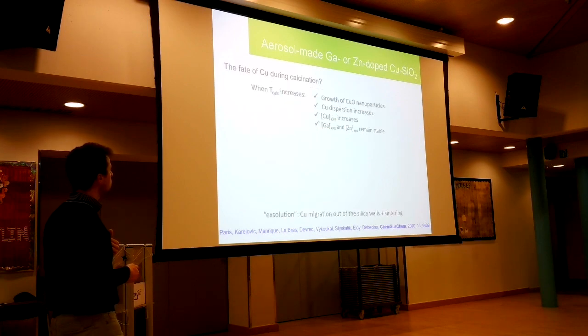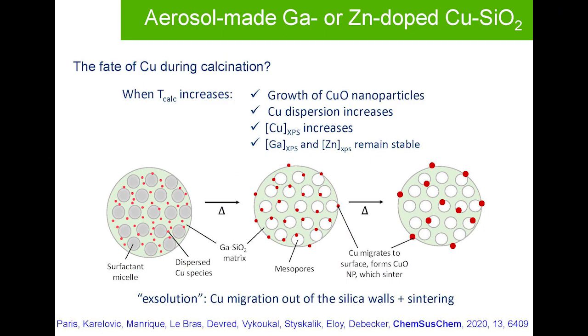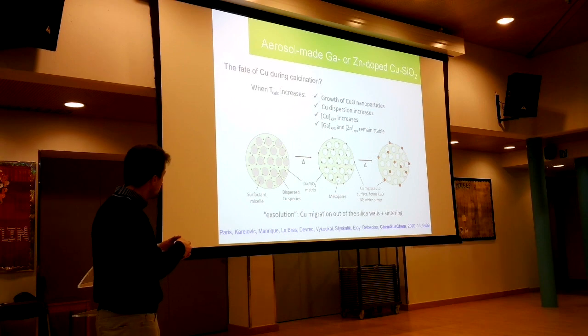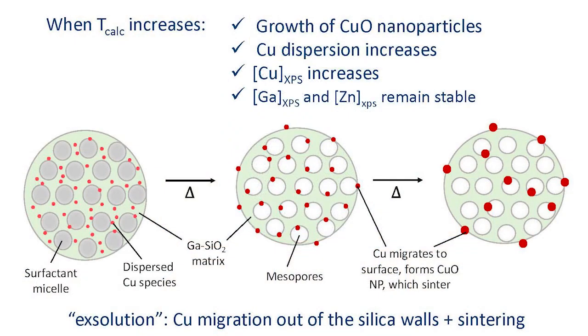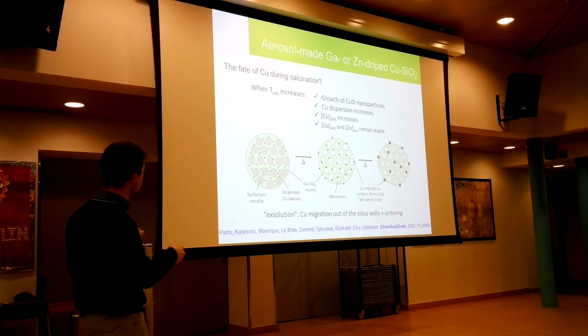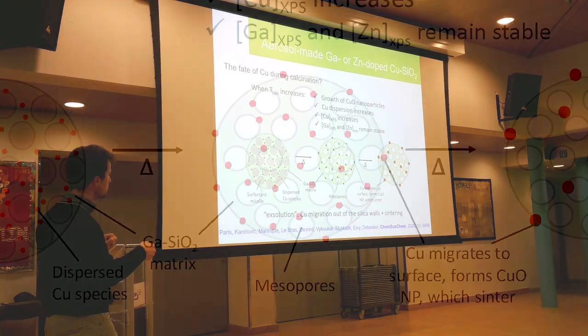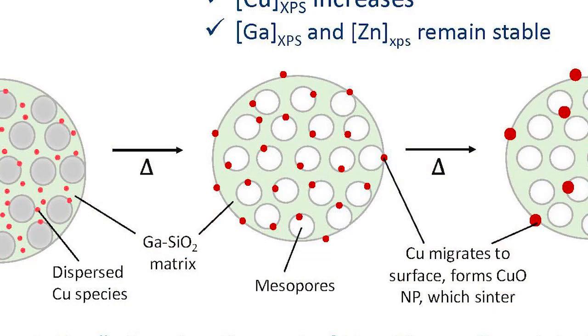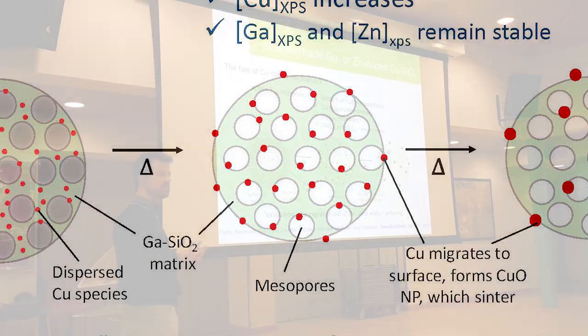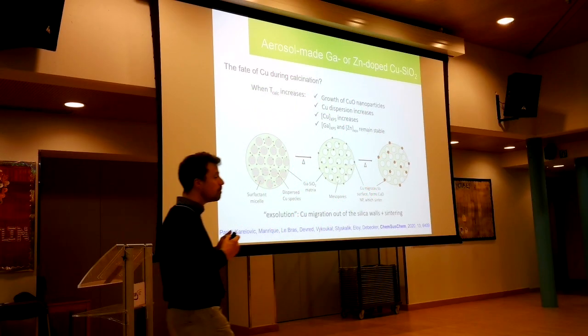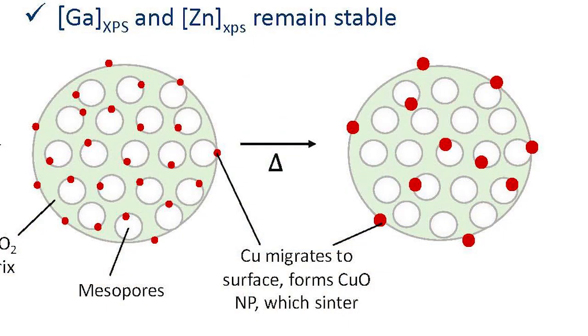Okay. Cutting a long story short, and I will not spend time to explain everything that we found there, but what we could explain or demonstrate is that actually in the spray, we disperse the copper atomically in the silica first. Those gray circles here represent the micelles, so the surfactants. And then we have to calcine to remove the micelles and to have the porosity. But by doing so, the copper does not like to be in silica actually. And it tends to migrate and go to the surface and form a bit bigger particles, right? So that's what we saw in the previous plot.